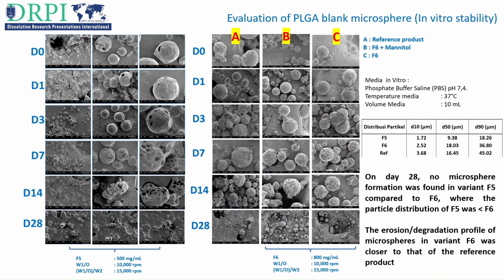A stability study was carried out between two formulations. It's F5 with PLGA concentration of 500 mg per milliliter and F6 with 800 mg per milliliter. In vitro stability testing over 28 days showed that the erosion or degradation profile of microspheres at 800 mg per milliliter PLGA was closer to that of the reference product. Therefore, this concentration, 800 mg per milliliter PLGA, was selected for Leuprolide acetate encapsulation.